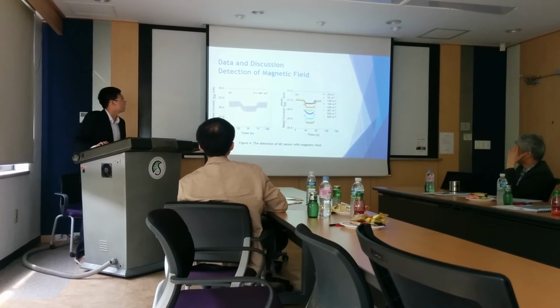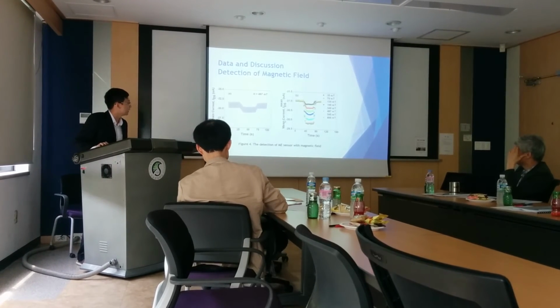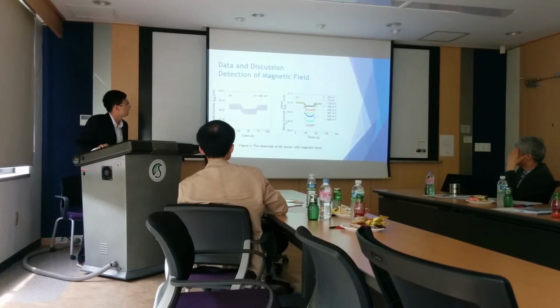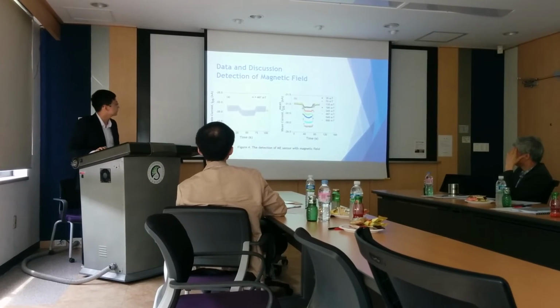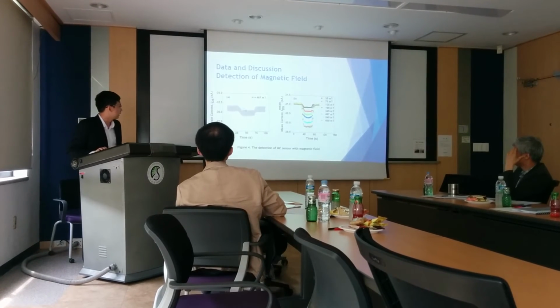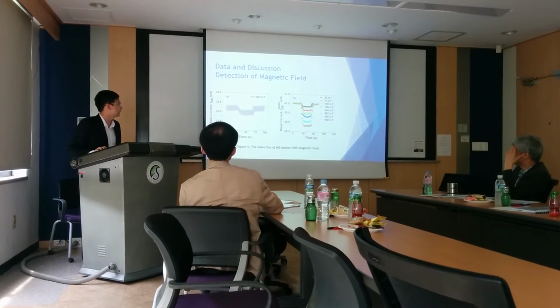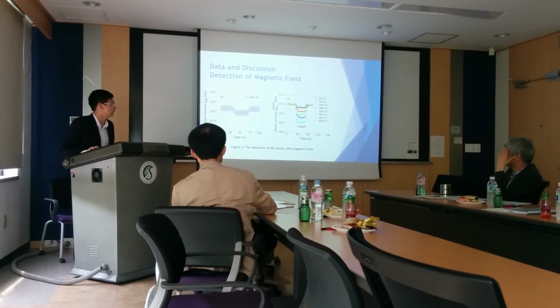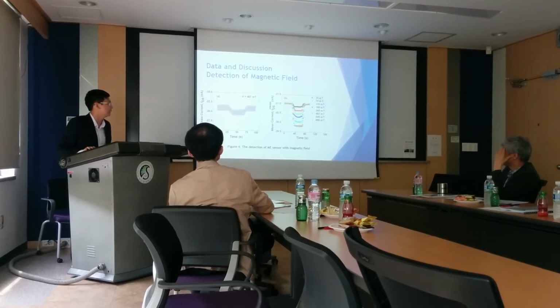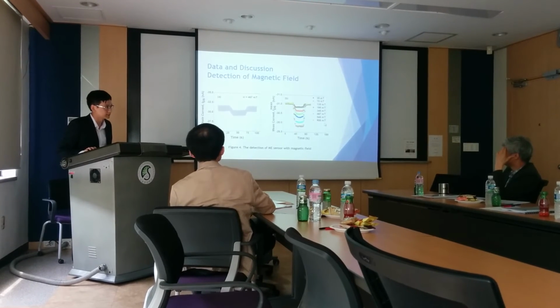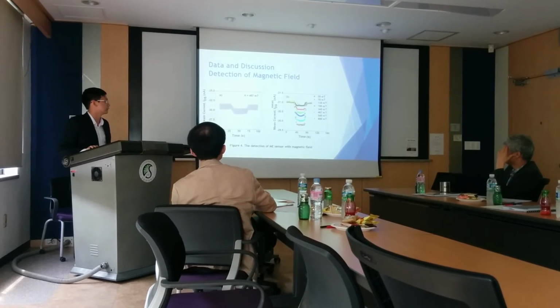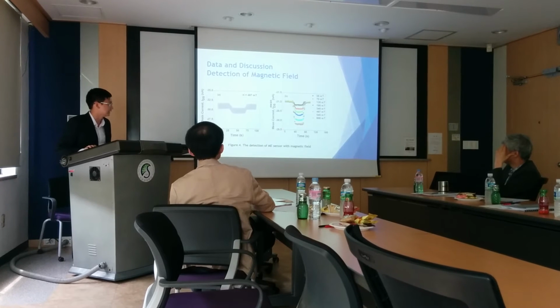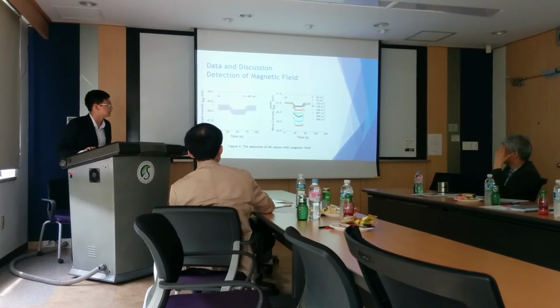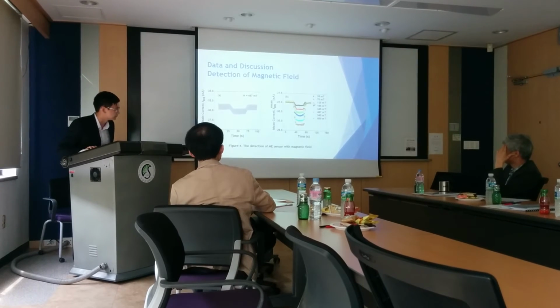This is the data of the current response of the MEOFET. As you can see, with different magnetic field intensities from 35 millitesla to 600 millitesla, they show the current response decreasing under the magnetic field and recovering to the baseline without the magnetic field.